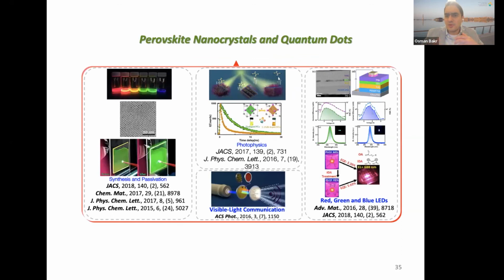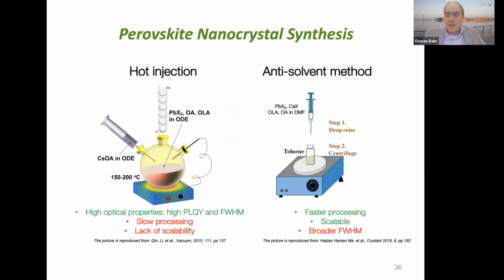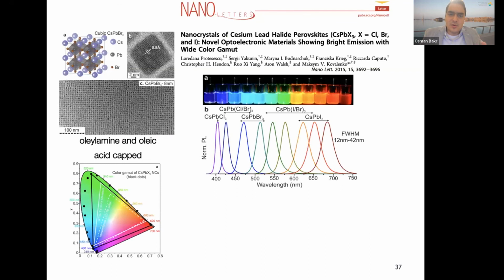So I told you a lot about single crystal solar cells. Now I'm just going to tell you quickly about what we did on some nanocrystals, based on perovskites. Instead of large single crystals, you could make tiny nanocrystals that are single crystalline as well, using either a hot injection method or an anti-solvent method. And you create these nanocrystals that Maxim Kovalenko's group showed are monodispersed and have controllable colors. They're exciting because the color is very controllable. You can obtain almost any color in the color gamut, and so that's really good for LED applications.